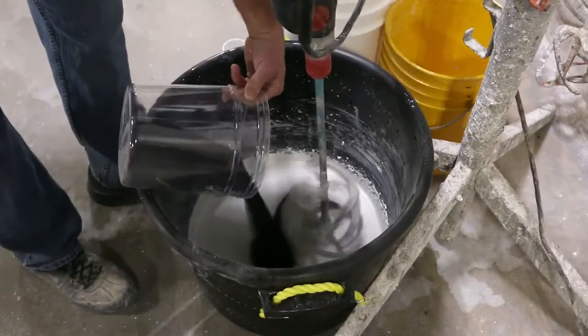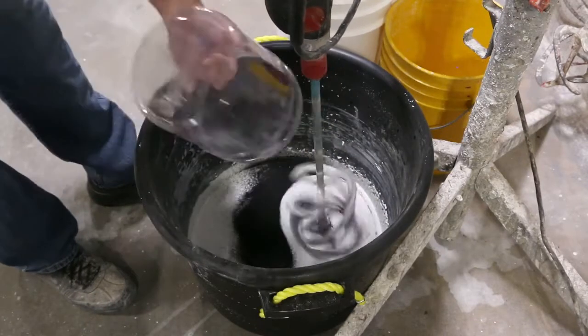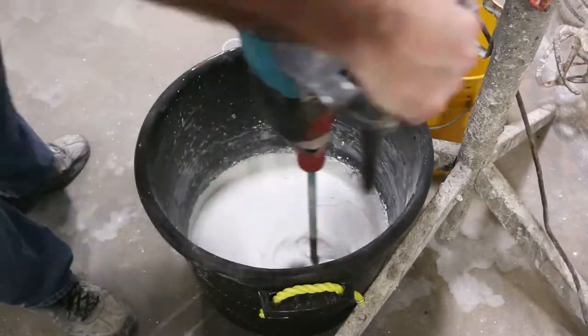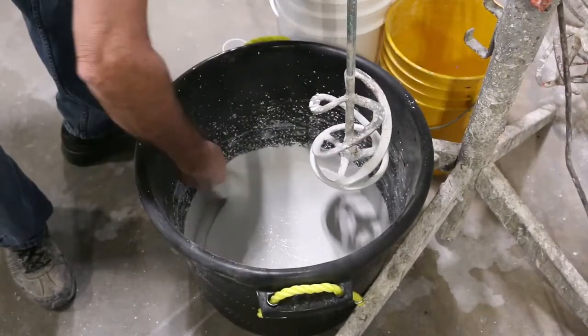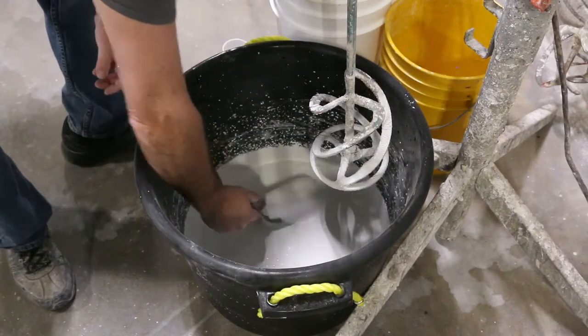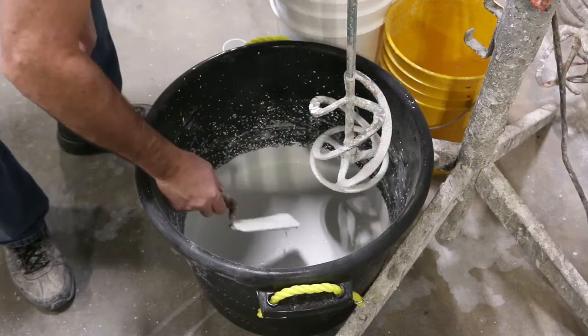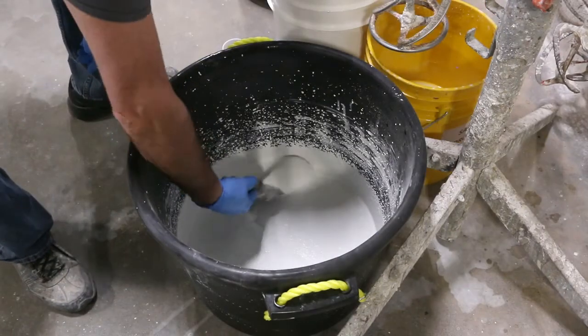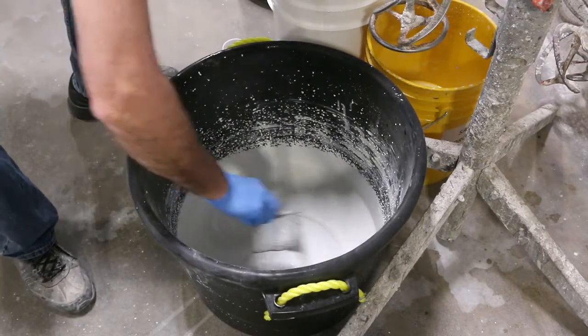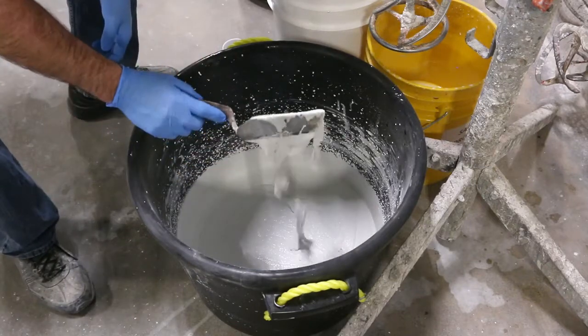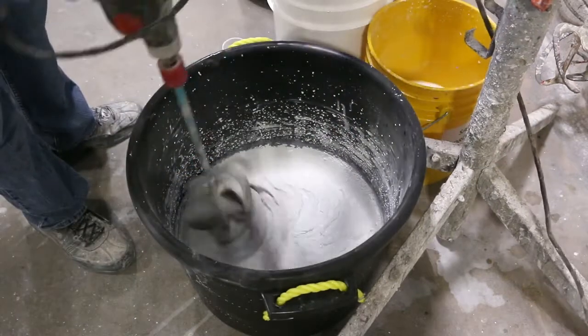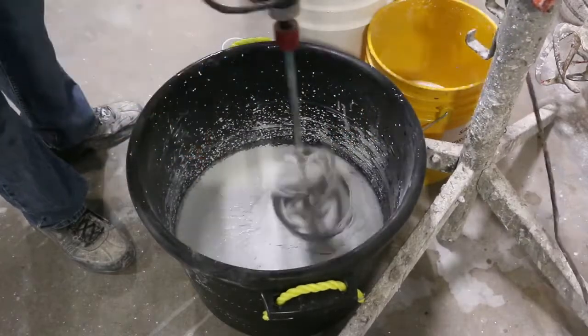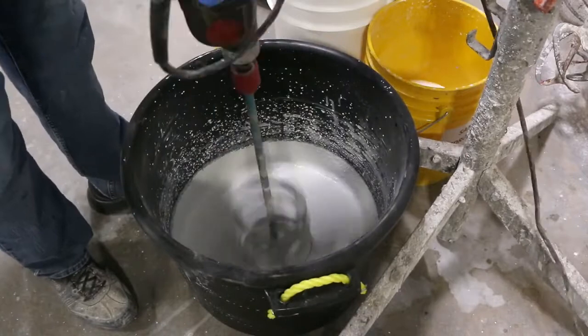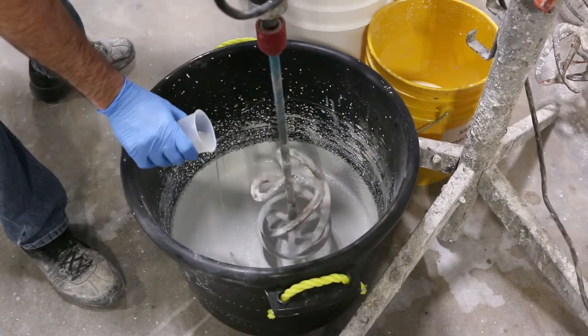I then added the black sand and blended well. I chose to add this at the end so the mix would stay as brilliant white as possible. Cement-rich concrete mixes often experience a condition called false set, which is a premature stiffening of cement within a few minutes of the introduction of water. This condition can be easily adjusted simply by remixing to regain fluidity. So after waiting 10 minutes, I remixed and adjusted with water reducer 420 as needed.